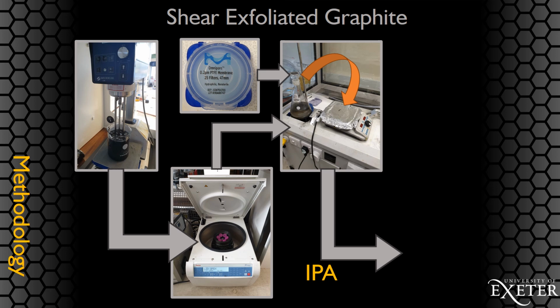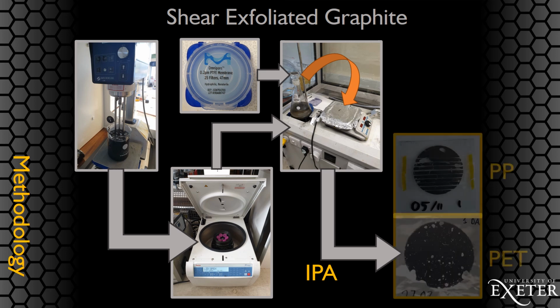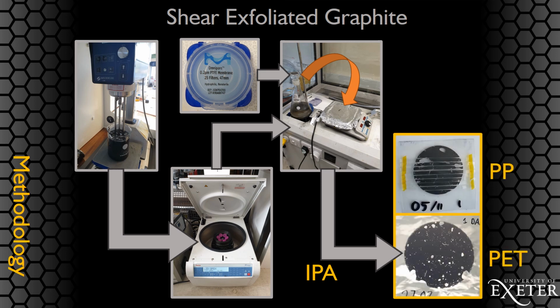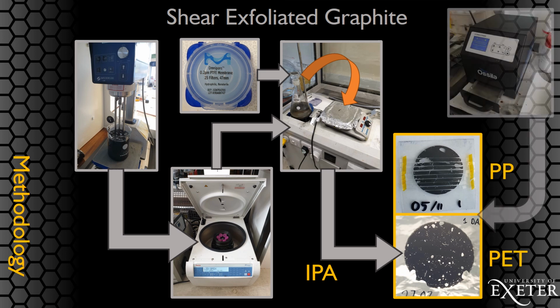The IPA aids the transfer onto the substrate, and once dry, the membrane can be peeled back to reveal a successful transfer, as you can see for both PET and PP fibers. The substrates can undergo a UV ozone clean prior to IPA transfer. Oxygen radicals bombard the surface and make the substrate more hydrophilic, improving adhesion to aqueous coatings.